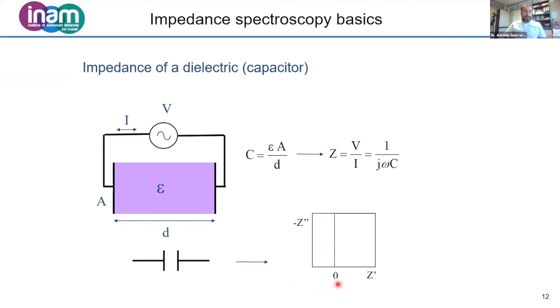If instead of a resistor you have a dielectric material, so basically you have a capacitor, the capacitance, using physics from textbooks, is the permittivity of the material times the area of the electrode divided by the thickness of the material. You can measure that in impedance spectroscopy, again, by dividing the voltage by the current that you measure. In this case, you will see this capacitor as a vertical line, because the capacitor does not let the current go through. The current will, in the limit, be zero, so this goes to infinite. As this goes to infinite, this shows as a vertical line.